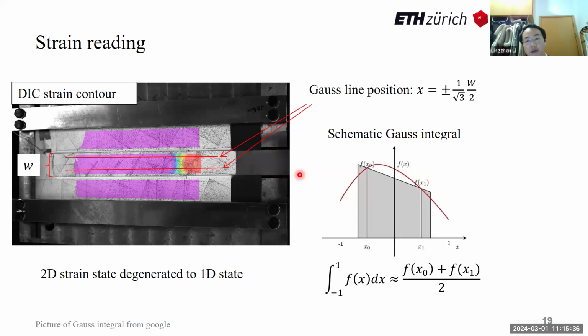So I used a technique called Gauss integral. The idea is that if these contours are an exact parabolic shape, then the strain values on these two Gauss points reflect the exact integral. If it doesn't follow an exact parabolic shape, such a Gauss integral could also approximate the strain integral behavior very well, so that we could simplify the 2D strain problem to a 1D problem.